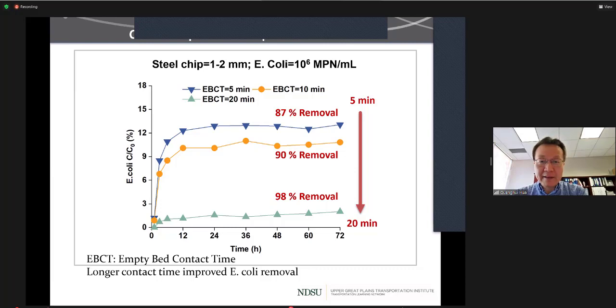So here we also look at the impact of contact time on the removal of E. coli through the column study. Once again, the y-axis indicates the ratio between the effluent to the influent. And I put the removal numbers for each of the lines for easy understanding. And we evaluate 3 contact times. EBCT means empty bed contact time. That's the travel time of water through the filter column. And we evaluated 5 minutes, 10 minutes, and 20 minutes.